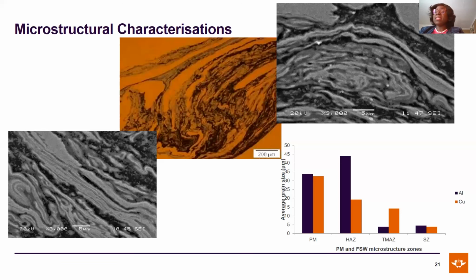We measure grain sizes because it's expected that in the stir zone we always have very refined grain sizes if our processing parameters have been very appropriate. So we measure the grain sizes across various zones, and we characterize them into various zones, which can be directly correlated to the microstructures of various zones of the welds.